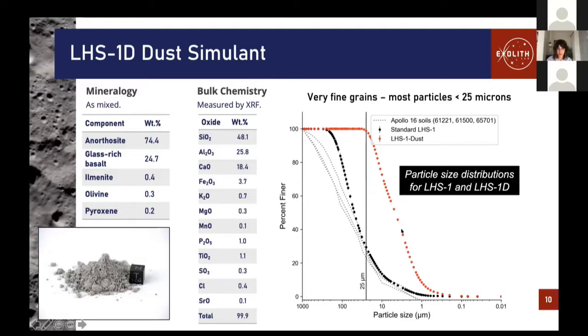So this is the particle size distribution for what we're calling LHS-1D, so our Highlands dust simulant. So the red star points here are the particle size distribution for the dust simulant. And this vertical line represents the 25 micron particle size. So nearly 100%, maybe about 98% of the material in the dust simulant is finer than 25 microns. And we have a comparable product for the Mare as well. Since it has a different proportion of the minerals, it takes a little bit of a different amount of time to crush it. So we're still narrowing in on that, but it's available soon. So that's that.